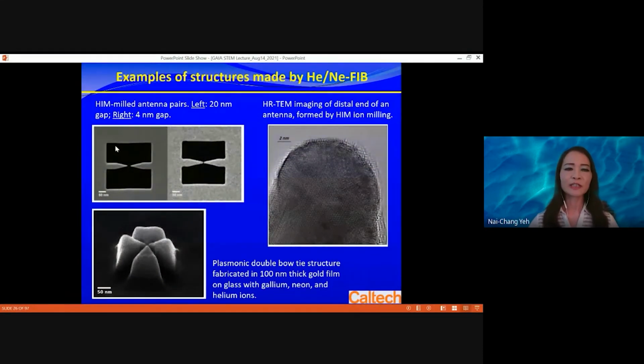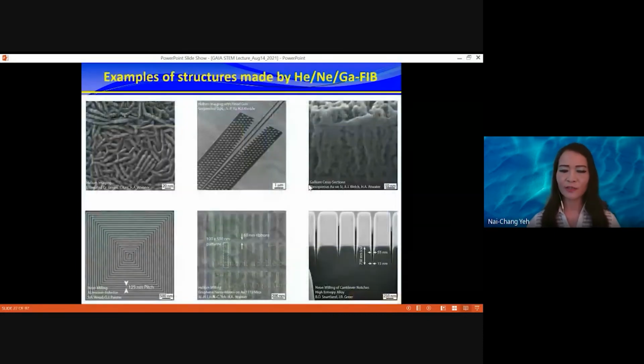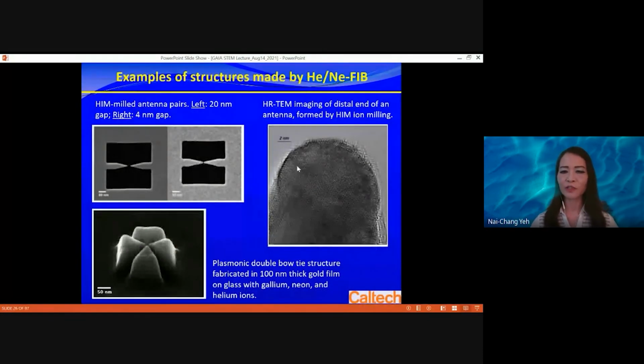Here you have a substrate, and you remove a lot of material here. For this part you use the gallium beam. But when you have these very, very fine structures, you use the helium or neon ion beam to create them. This is another picture showing helium techniques used to develop an antenna. And this is a picture taken with transmission electron microscopy. You can see atoms. This scale is only 2 nanometers, and you can actually see atoms.